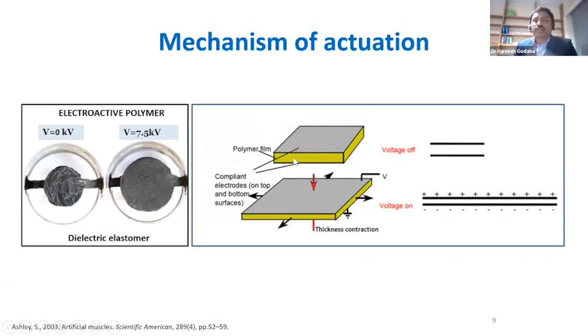So how it works is basically this is a stretchable polymer film, or as we call this class of materials, elastomers. So they can stretch and then they can recover their initial reference configuration when we remove the external loads. And then we coat this elastomer membrane with compliant electrodes. So electrode is basically conducting material on the top and the bottom of this film. And now when we apply a voltage across these two conductive layers, basically this is now like a parallel plate capacitor, right? So there are charges formed, and there is an electric field that is formed along the thickness direction. And then you can imagine as if these charges compress this membrane, and because this elastomer is incompressible, the elastomer stretches in the area direction and basically this expands. So this is basically how this dielectric elastomer works.